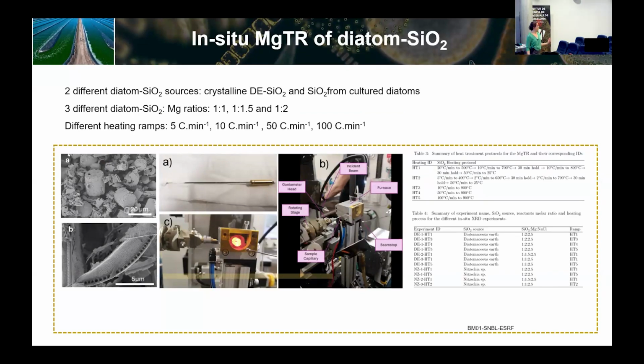So we went to the synchrotron and planned a bunch of experiments, not just one in situ, but 9 in situ experiments. We will try to see the effect of using diatomaceous earth or the Nitzschia species as a reagent. We will try to see the effect of using a different ratio, 1:1, 1:1.5, 1:2, between silica and magnesium. We will also try to see the effect of the heating ramp, how much that affects the formation of the byproducts. So we went to BM01 of ESRF.